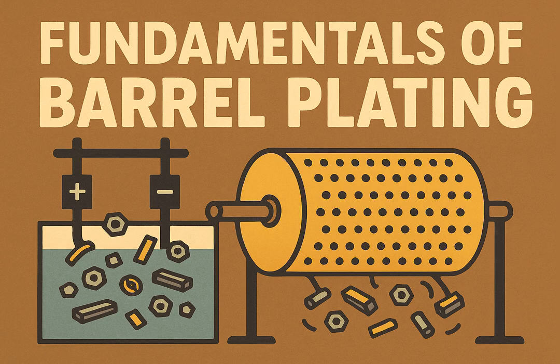The most common and widely used type of internal contact is flexible danglers. Danglers, like thick wires hanging down. Yes, often made of conductive materials, sometimes covered with protective insulation except at the tip. They hang down into the tumbling mass of parts. The sources emphasize that to get the best plating results and prevent issues like arcing or burning, these danglers must be properly submerged within the workload of parts. So they need to be deep in the pile of parts. Exactly. If they're just floating on top or making intermittent contact as the load shifts, you get inconsistent current distribution, which leads to uneven plating.